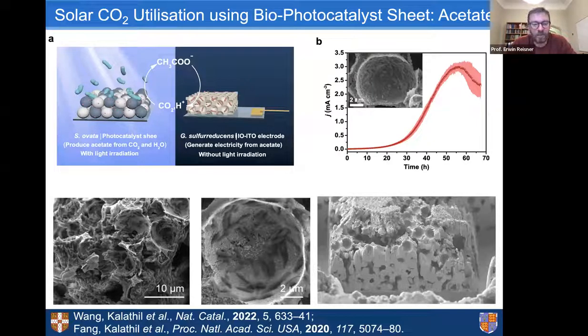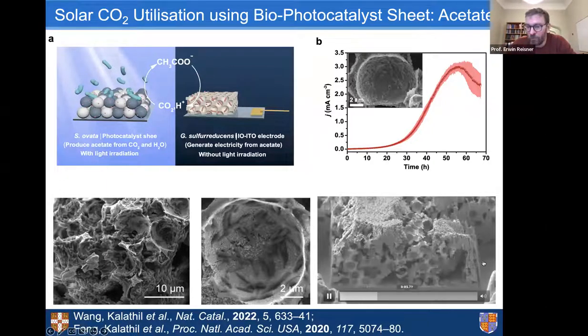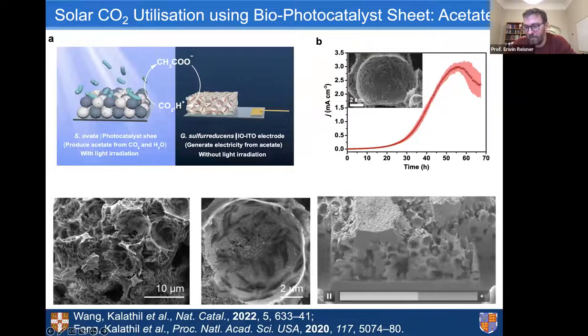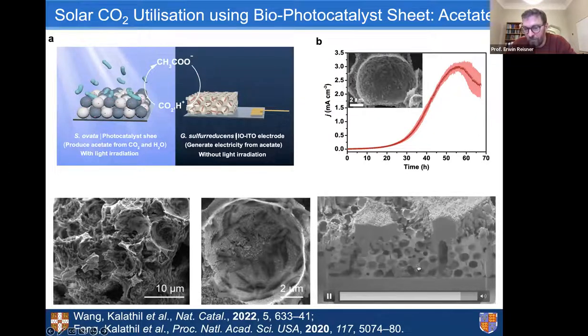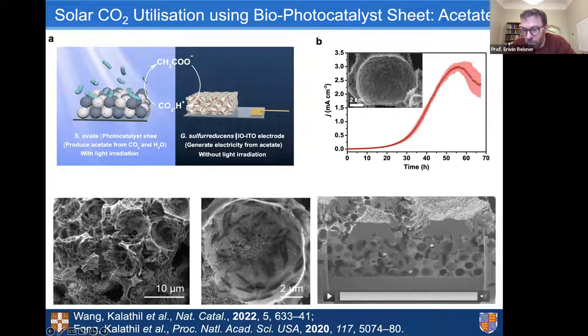They have a very well-developed electron transport mechanism in and out of the bacterium through the cell membrane. So they grow little nanowires that are conducting, and you can actually push electrons in or pull electrons out by applying different voltages. And these bacteria grow nicely in the pores. You can see this focused ion beam SEM on the bottom right, where the soft matrix is the bacterium and the smooth part really is the electrode. So it really penetrates the whole structure. These are about 10 micrometer pores, and the film thickness is about 20 to 40 micrometers.